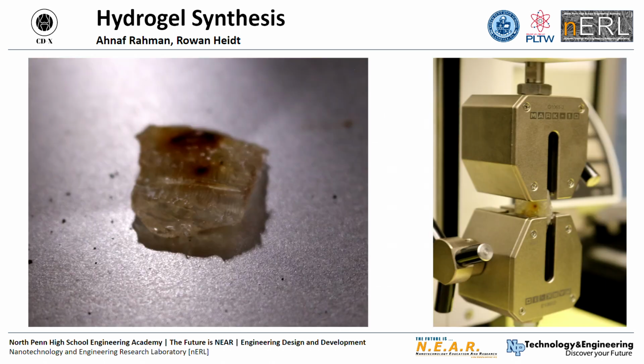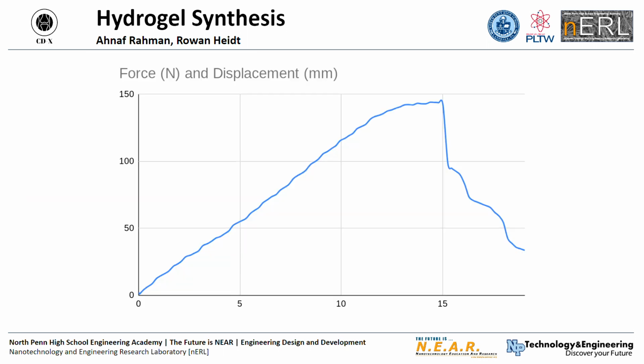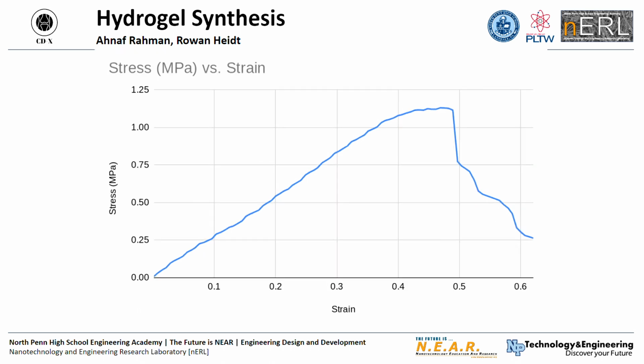Here's the second sample we tested, which performed much better than the first. When we ran it through the tensile tester for the first time, we had an ultimate tensile strength of about 144 newtons before it slipped out of the clamps of the tensile tester. And if we translate that over to stress and strain, it's about 1.16 megapascals.